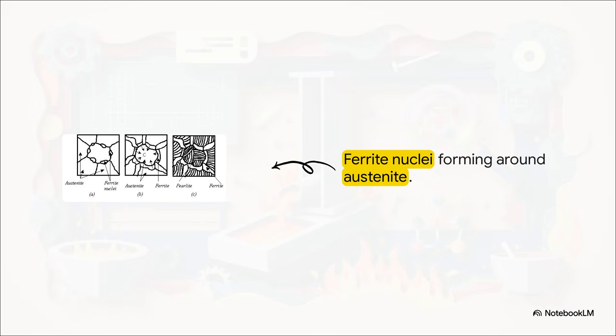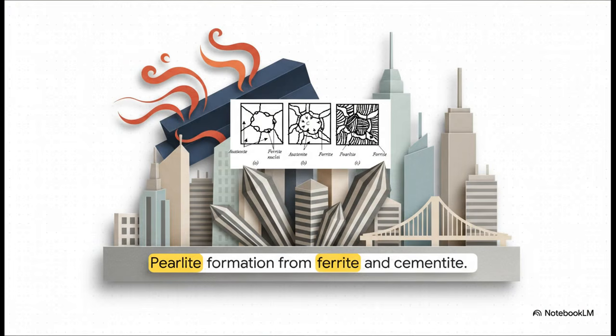Up at around 900 degrees Celsius, our low-carbon steel is hanging out in a phase called austenite. Now, as it begins to slowly cool down in a furnace, a transformation kicks off. Soft, virtually pure iron, which we call ferrite, starts nucleating, or forming, right around the boundaries of those high-temperature austenite grains. It's really cool. You can basically see the little clusters of ferrite just grabbing hold at the edges. So let's see how this builds. By the time the steel fully cools all the way down to room temperature, the remaining austenite undergoes a massive change. It transforms into something called pearlite. Pearlite is this stunning, tough, striped mixture of soft ferrite and hard iron carbide. And it's this exact lamellar, or layered, structure that provides the actual mechanical muscle and everyday strength in the structural steel holding up our cities right now.